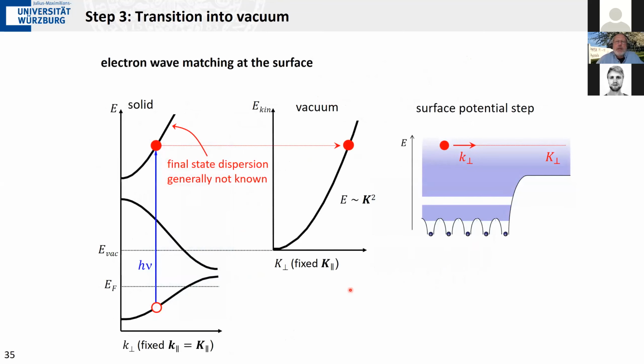And that can be understood very easily as the electron goes from somewhere in the interior to the outside here. You see that it changes kinetic energy, because here our energy reference is the bottom of our band. Here it is the vacuum level. And so the perpendicular momentum changes, or in terms of band structure, this is the band structure as a function of K perpendicular at a given value of K parallel, which is conserved, which may have this structure here.